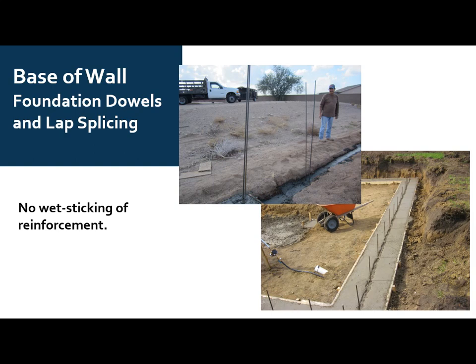One thing I do tend to see a fair amount is what contractors occasionally call wet sticking. So they place the grout, they place the concrete, and they come in after the fact, and then they place the reinforcing steel. So there's really no code, whether it's a concrete code or a masonry code, that allows for that type of construction practice. And I get why, it's a little bit easier to do because you've got the concrete already placed. Once it starts to stiffen up, you can drop a rebar in there, and it kind of stays in generally that position that you apply it.